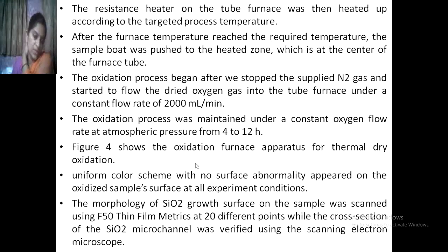So the morphology of the SiO2 growth surface on the sample was scanned using F50 thin film metrology at 20 different points, while the cross section of the SiO2 microchannel was verified using a scanning electron microscope.